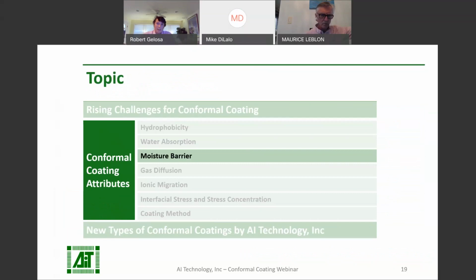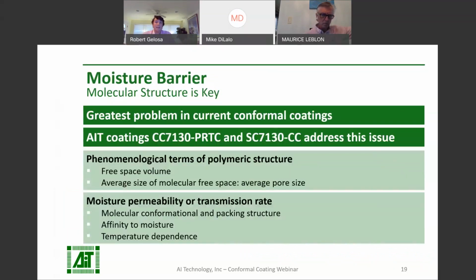So many conformal coatings out there address the issues of water absorption and hydrophobicity, but moisture barrier properties are largely neglected in the industry. The moisture permeability, or transmission rate of water in its gaseous form through a conformal coating, is a reflection of the molecular structure of the polymer. Greater free space volume and larger pore size will lead to higher moisture permeability. The moisture permeability is also dependent on the temperature and the thickness of the coating.